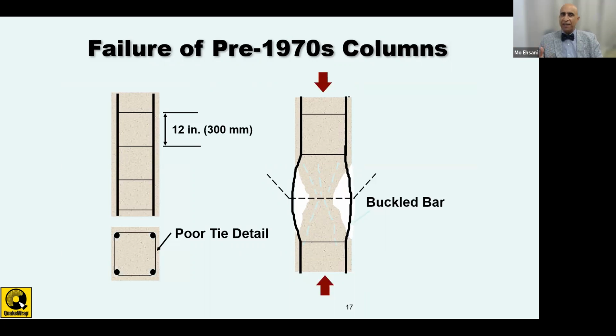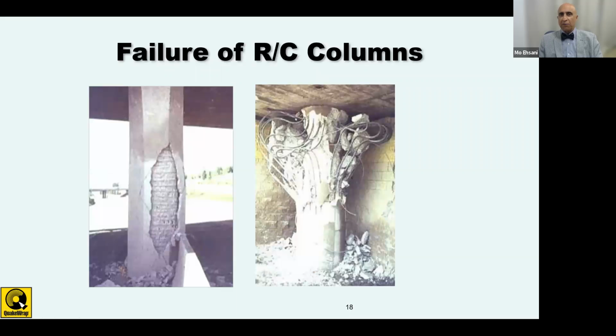Application of these products in columns basically started with some of the seismic work after the collapse of some of these bridges. In the older ACI code, for example, columns, regardless of size, required a tie every 12 inches along the height of the column. Also, the ties usually had a detail without the 135-degree hooks like we require today. This poor detail resulted in the ties opening up as you load the column, and then the longitudinal bars would buckle. Some of the older columns, if they are spiral, perform well, but the tied ones, as you see here, do not hold so well, and they crumble and crush quickly.